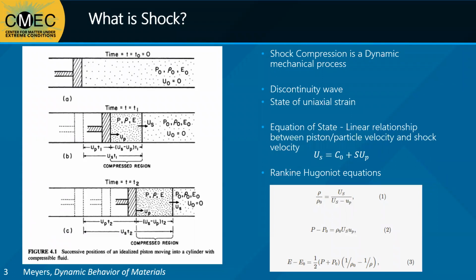Shock waves in experiments can reach extremely high strain rates of up to 10^8 or 10^9. The large strain rates may suppress other more conventional deformation modes, such as fracture. This can lead to shock compression experiments having unexpected results, such as dislocations or phase changes that are not predicted from static compression or equilibrium conditions. These high strain rates also lend themselves to be very complementary to molecular dynamics simulations.